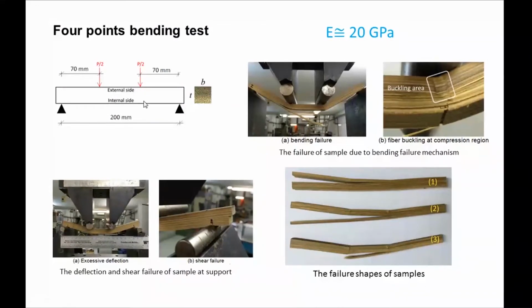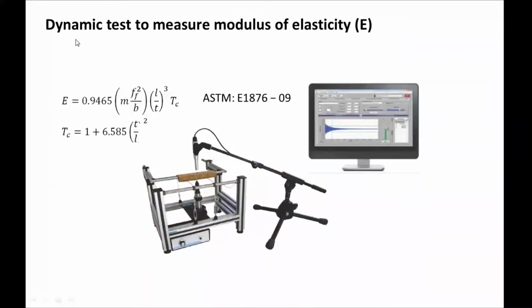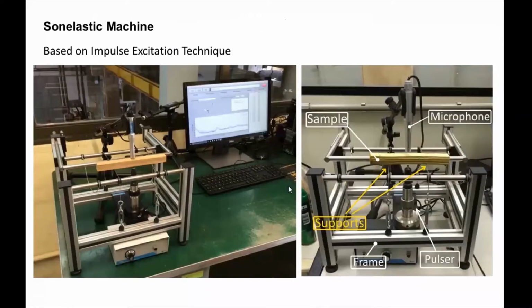And we have the 4-point bending test, and we found that the modulus of elasticity is about 20 gigapascal, and you can see the failure shapes of the samples with low wall thickness and with high wall thickness. We can see shear failure happen for the samples, and different types of failures. And we can also use a dynamic test to measure the modulus of elasticity. It's a sonelastic equipment made in Brazil, by a professor here, and we use it to measure the mechanical modulus of elasticity based on the impulse excitation technique. The sample vibrates, the sound produced by the sample is recorded by the microphone, and after analysis, you can understand the mechanical property of the sample.